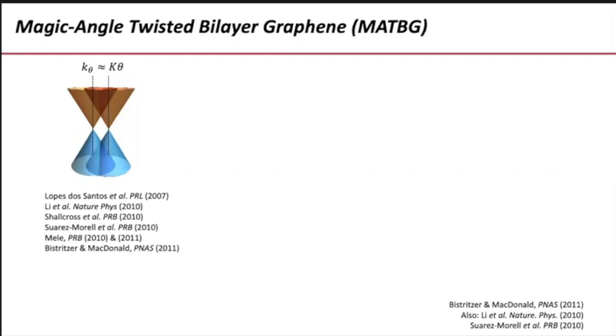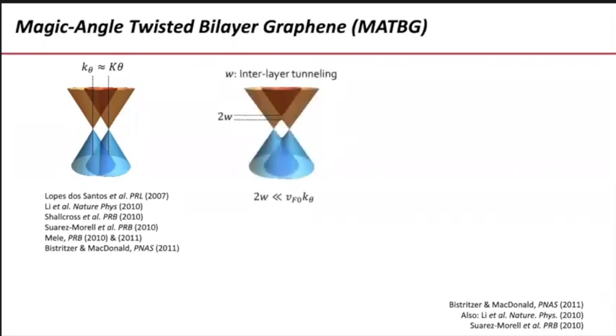However, because when we put graphene on top of graphene, these graphene sheets are just 3 angstroms apart, electrons are very much aware that the other graphene sheet exists, okay? And in particular, they can tunnel between the two graphene sheets. This leads to a band repulsion at that crossing point, and it is due to this interlayer tunneling. The situation depicted here is when that band repulsion is smaller than the energy of that crossing point. This is the same thing as bonding and antibonding states for a hydrogen molecule, except that it is bonding and antibonding bands for a giant graphene molecule.